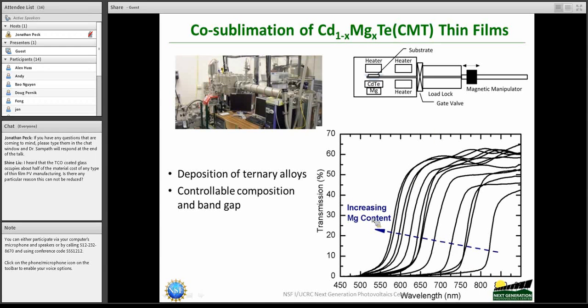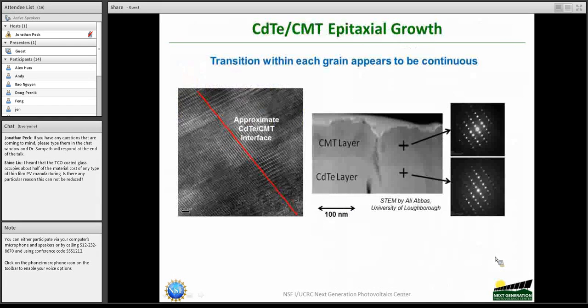And what is shown here is that if you run this magnesium source hotter, you can add more and more magnesium and increase the band gap of the material, and then as the magnesium content is lowered, you get a lower band gap material. And one of the fortuitous observations here is that when we deposit this cadmium magnesium telluride layer on cadmium telluride, we see that the interface is quite continuous at atomic scale. There is no abruptness between these two layers, and this is kind of needed to make this whole thing work electronically.